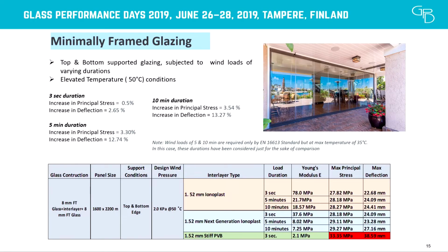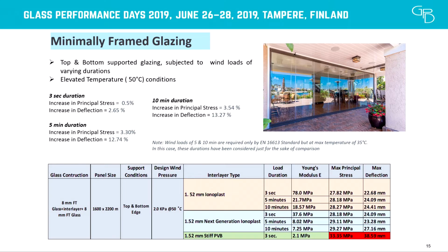The next one is higher temperature. Remember, one of the goals was to maintain the structural properties over a broad range of temperature and loads. So this is at elevated temperature, which was our bigger concern. Here we have current Ionoplast and next generation. And here you have, at a 3-second duration, a 0.5% increase in stress, and at 5-minute duration, 3.3%. So a little bit more, as expected. But then you take a look at your stiff PVB at the 3-second load duration, and with the modulus that it has, you have a significantly higher deflection. So the next generation does have a little bit more deflection and a little bit more stress, but still very high modulus and very good structural performance.